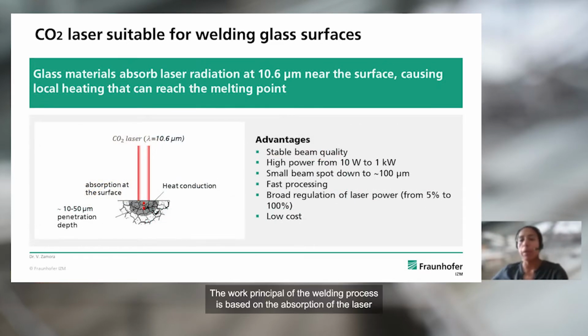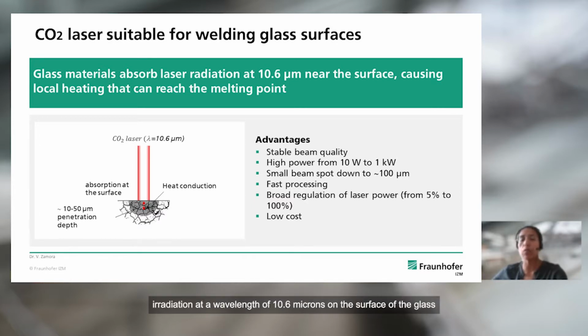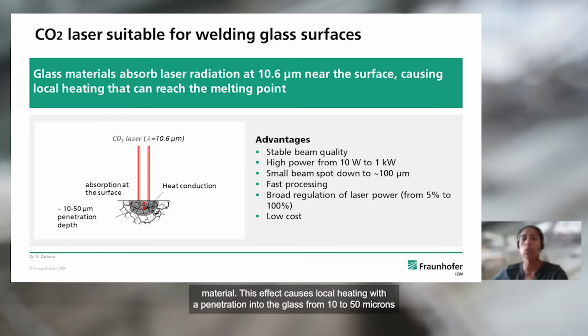The working principle of the welding process is based on the absorption of the laser irradiation at a wavelength of 10.6 microns on the surface of the glass material. This effect causes local heating with a penetration into the glass from 10 to 50 microns, which can reach the desired melting point. For this approach, CO2 lasers are the best candidates because they provide stable beam quality, broad power range, small beam spot, fast processing, broad regulation of laser power, and low cost in comparison to other lasers.